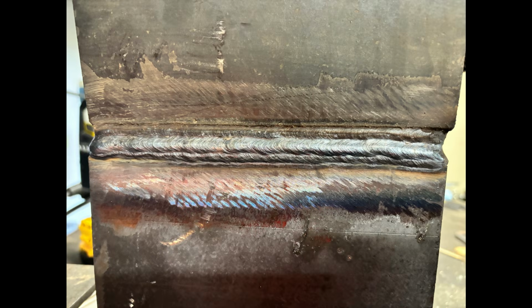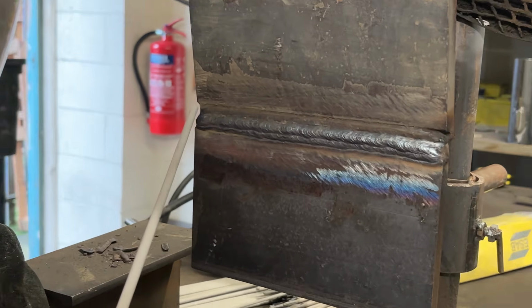Now we're on to our third pass, continuing the same process, stacking neatly on top of that previous run to keep our weld building evenly. We're maintaining a drag angle, keeping that flux at the back of the pool, and we're holding quite an acute up angle to help defy that gravity. We have to be careful on this run as we don't want to stray too far from that top edge, otherwise it can make it difficult for our final pass to properly catch the top of that prep.